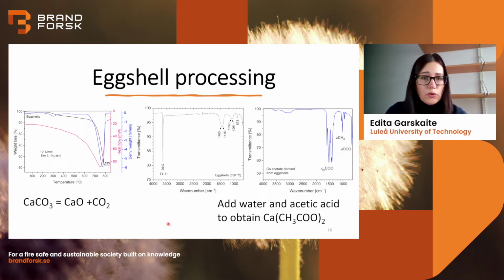So we also performed infrared analysis of this calcined material. We adjusted our process, and then when we got the calcium oxide, we prepared calcium acetate, and here is an example of infrared spectra which we received, and it shows characteristic bands for acetate ions.